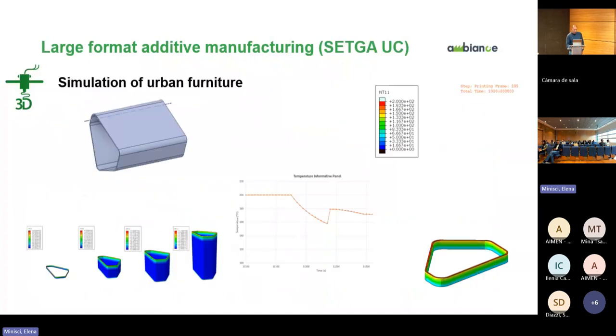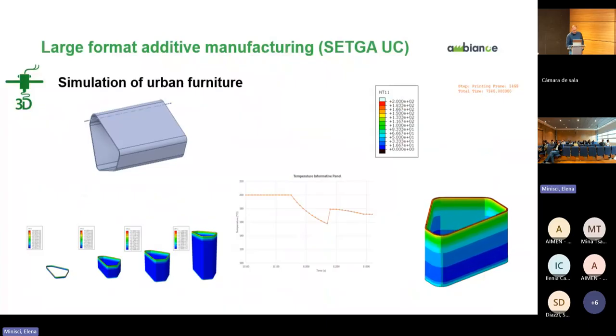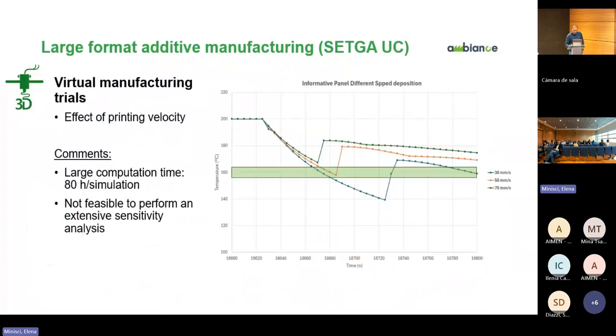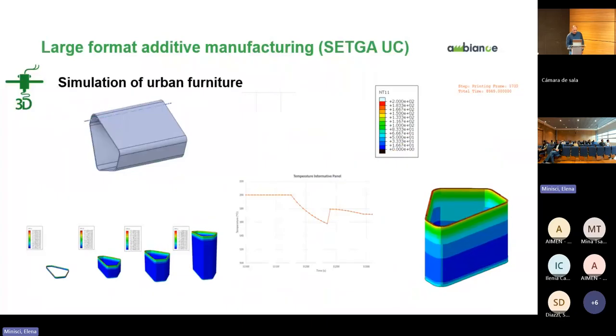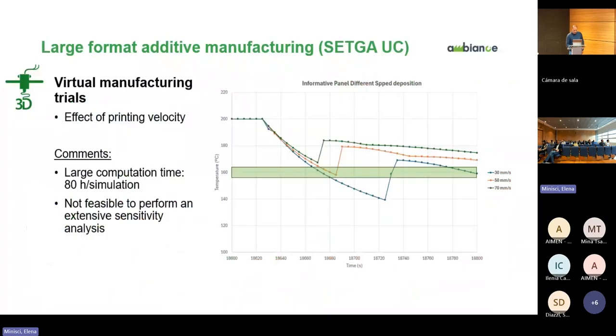For example, we have here one of the simulations of one of the furnitures. This is an informative panel, a support to show something on. And here we can see how it's building, again layer by layer, and how the temperature is evolving continuously over time. And again, we have here the typical curve where we analyze the temperature drop at the cooling between one layer and the next one. Here, for example, we have used this model to analyze the effect of changing the printing velocity, to slower velocities and to higher velocities. And we can see here the effect.